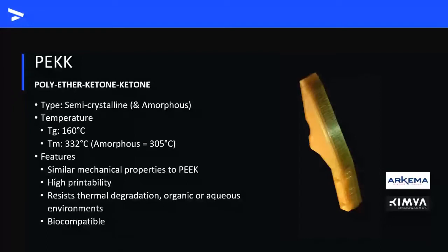PEKK is another PAEK family member, but unlike PEEK, PEKK is a copolymer with a crystallization rate that can be tuned via the ratio of terephthaloyl and isophthaloyl. It has a slightly higher glass transition temperature of 160 Celsius, and the melting point is 305 Celsius degrees for its amorphous grade, and a melting point of 332 Celsius degrees for its semi-crystalline grade. The amorphous grade has such a slow crystallization kinetics that it can act like an amorphous polymer.